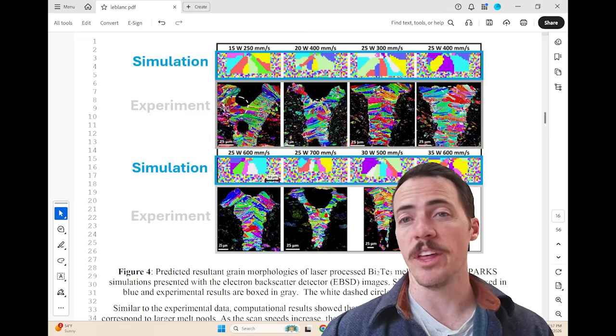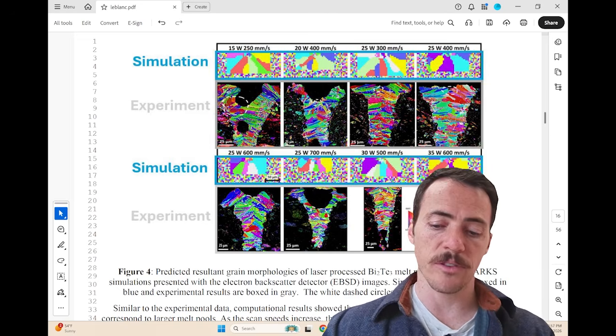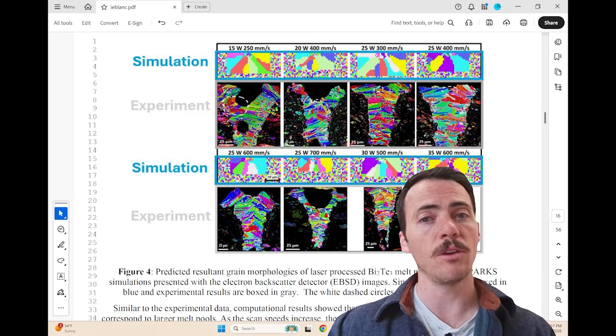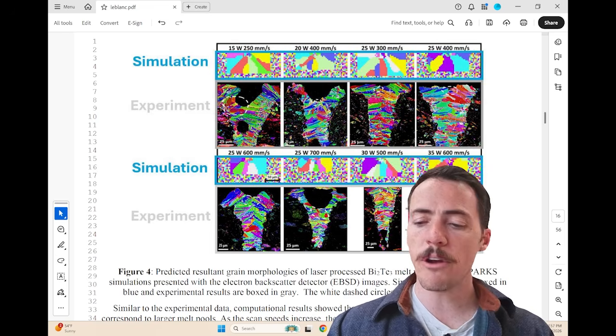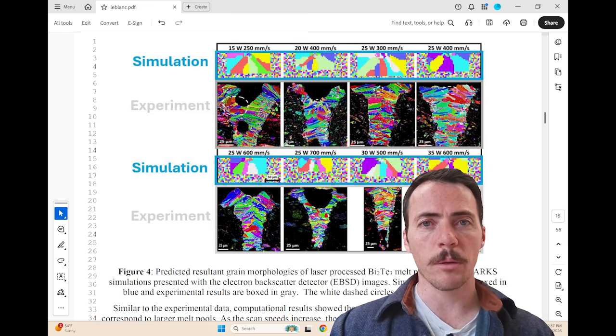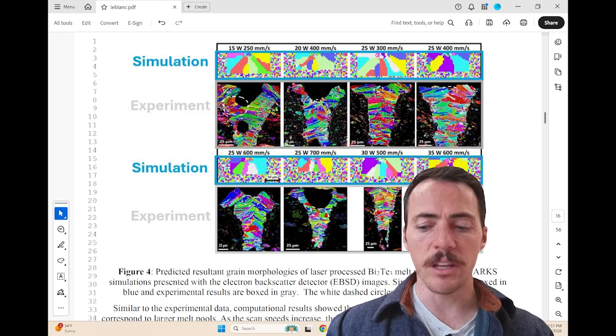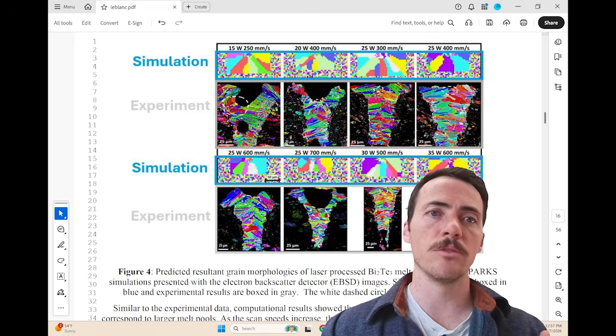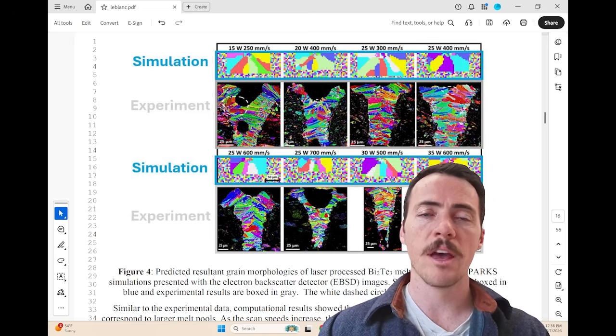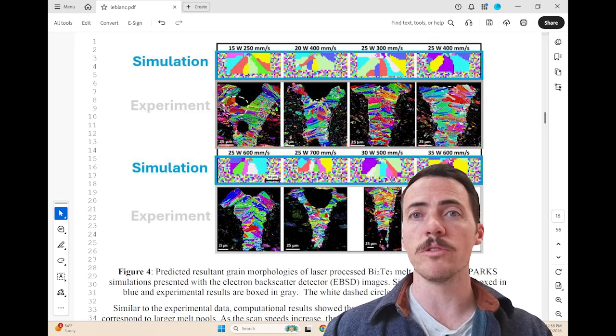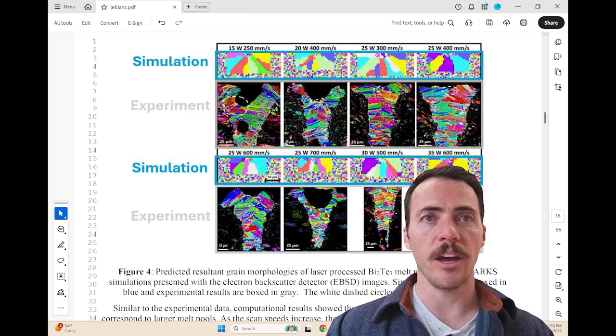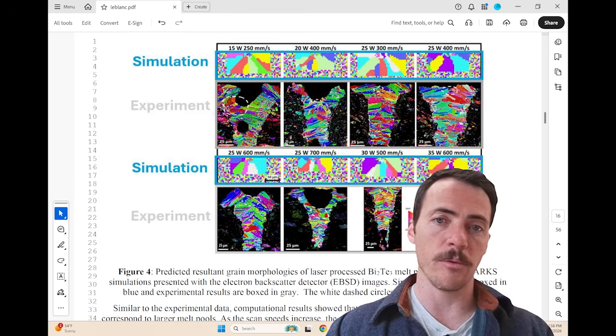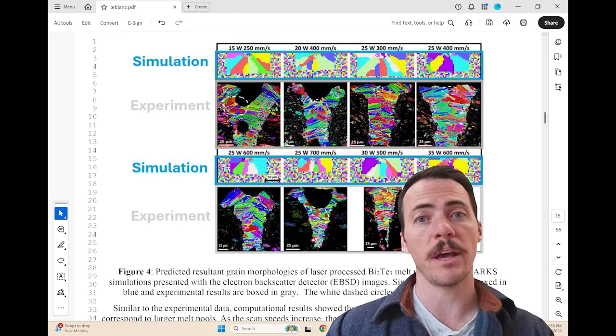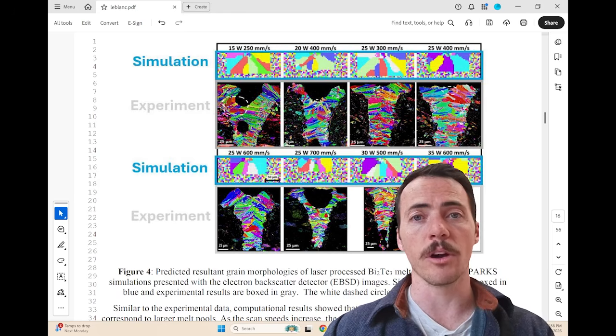They did point out that it did not match well as you enter this Marangoni flow or in the keyhole regimes. So the takeaway for me is pretty interesting. Essentially what I'm learning from this paper is that it is going to be possible to use some of the similar tools we built for metals, but we have to know when we're using those in the right regime. And if you pass over into the different regimes, right, in diffusion dominated, it's one thing, but when you pass over into the fluid flow regimes, they're simply not going to work well.